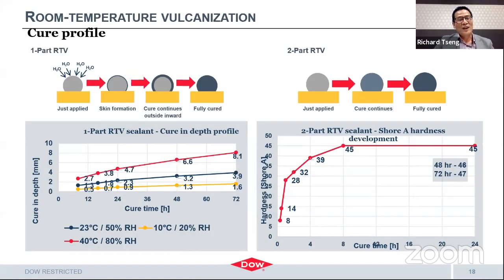To understand more of the silicone process, I would like to share a little more about how one-part RTV, room temperature vulcanization, cures when you use it on your product. When one-part RTV is dispensed on the substrate, it reacts with the moisture from the air, so it starts forming a skin. Over minutes, it forms a thicker cure, and it needs about 24 hours to be fully cured. It is a slow curing condition, but it fits a lot of manufacturing processes, especially assembly and component fixing, without any issue.